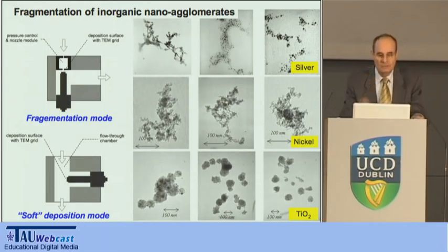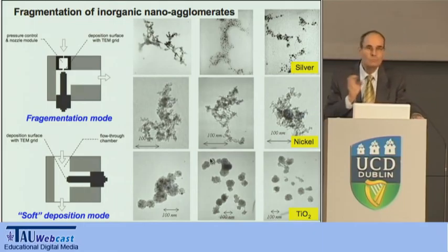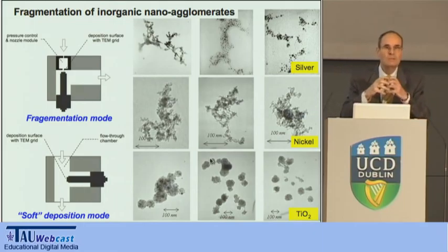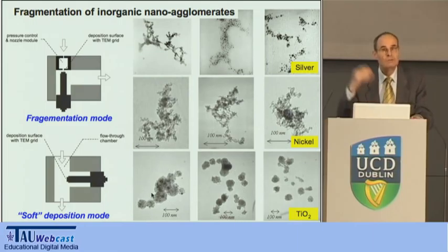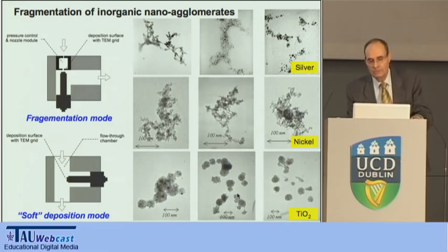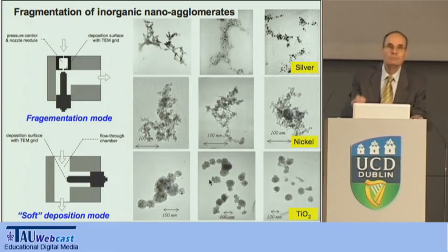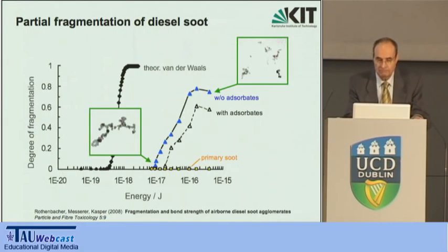the primary structures of this titanium agglomerate here were really sintered due to the production process sufficiently to never come apart again. But let's say if this was the aerosol particle that would have entered the lung fluid, and I'm now trying to build a bridge, would it then in the tissue fluids have perhaps broken up into these constituents and not any further? And would those actually be the mobile subunits which you should be looking for when it comes, for example, to crossing the boundary across a cell boundary or the likes?